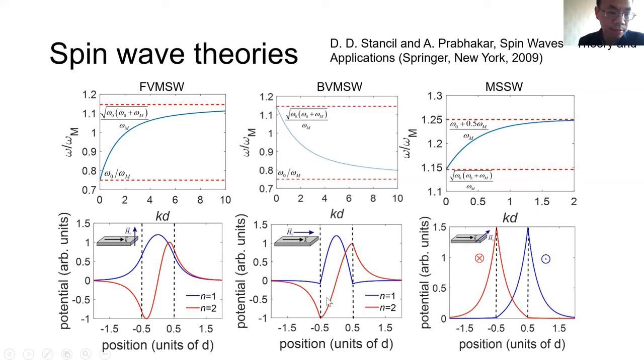Here I give some major conclusions about the three kinds of spin waves, according to the wave vector directions and the external field. Firstly, when the external field is out of plane of the magnetic film, this wave is called the forward volume spin wave. And when the external field is in plane and parallel to the wave vector, it's